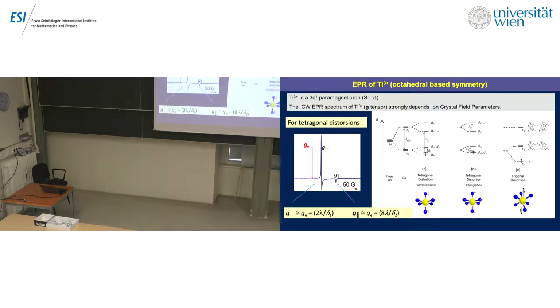So the spectroscopy is not so complex because titanium 3+ has a 3d1 configuration, and so is a one-half system. Otherwise, if there are 2 or 3 or 4 unpaired electrons in the system, you can do EPR, but it's much more difficult. So I'm pleased to discuss such a case because it's less complicated. The g value depends on the symmetry of the environment and on the energy of the splitting separation that can be very different in various cases. So I just discussed not the tetrahedral case, it's not our case, but the octahedral case with the trigonal distortion in the sense of compression or elongation. This is perfectly ruled by the EPR theory, so there are no problems.